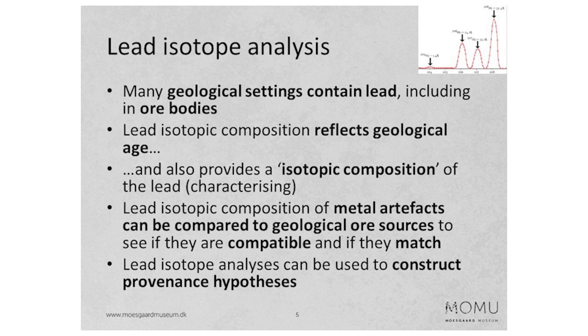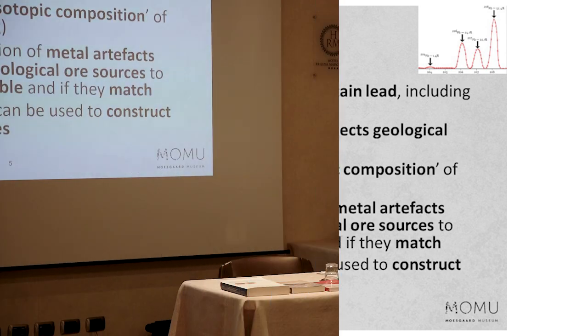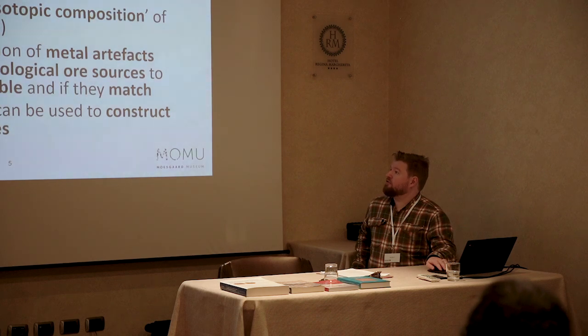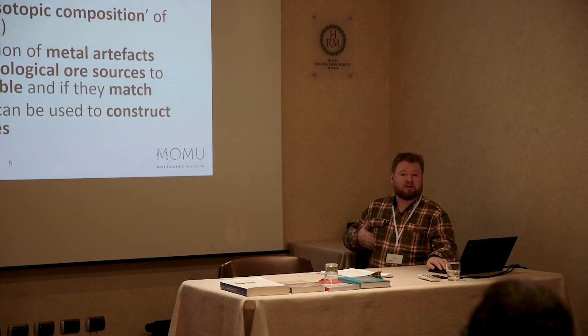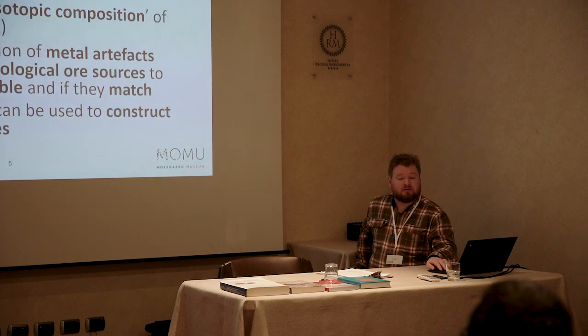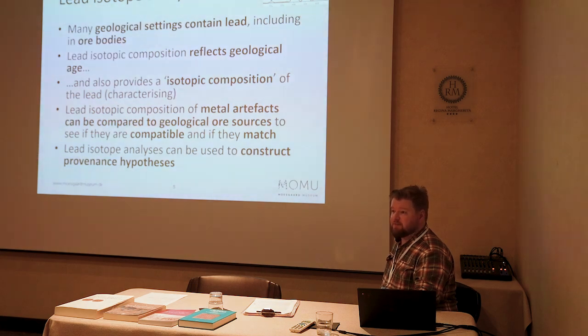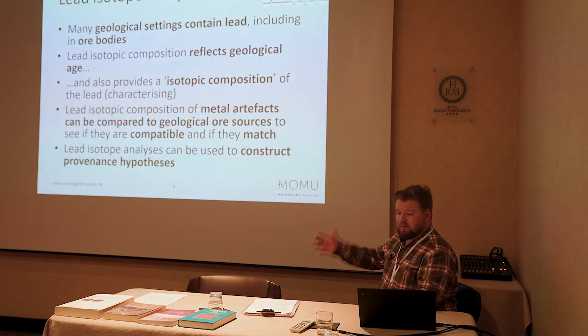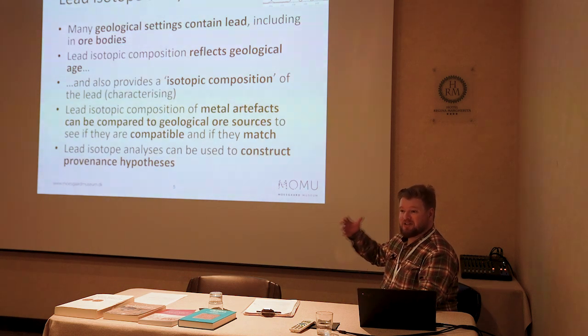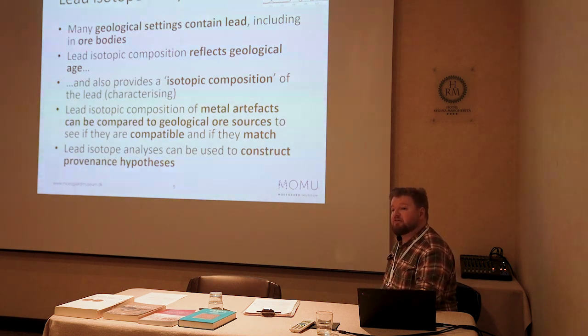Not all lead has a lot of silver, and some lead has a lot of silver. And so the threshold for what is considered to be argentiferous lead is debated, but the Romans were extracting silver from as little as 150 parts per million in the lead. So if you imagine you're melting down tons of this stuff just to get kilos.